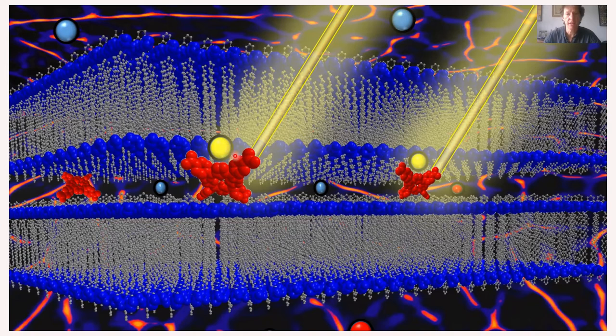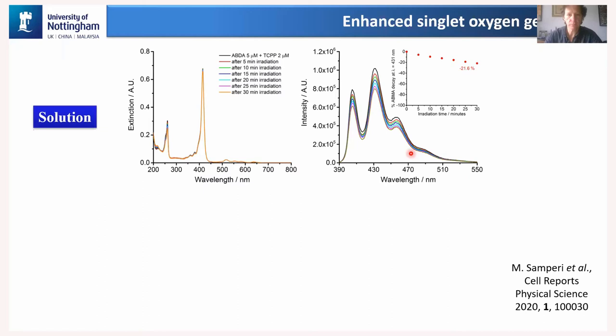And this beam indicates light coming in. It's going to excite the porphyrin, and the porphyrin is going to transfer its energy to the oxygen, make the singlet oxygen form, and then the singlet oxygen is going to go off and react with the anthracene compound. So first of all, to see the effect, let's just look at the porphyrin molecule in solution.